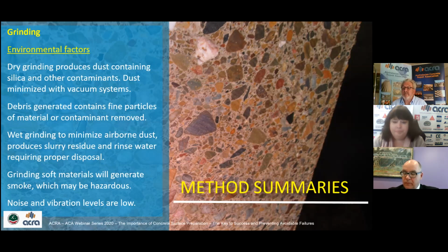Wet grinding can be used to minimise the airborne dust, but produces a slurry residue, which once again requires disposal, and you need to hit that with a bit of water pressure to get rid of that slurry. That can be a debonding factor for a coating or repair system. Grinding soft materials will probably generate smoke, and the noise level with that system is low.